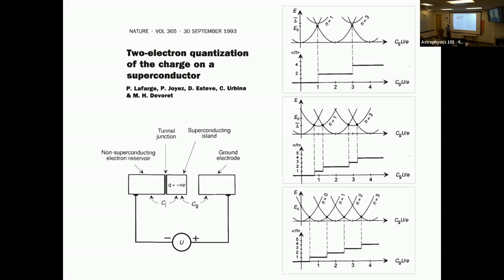But if the superconducting gap exceeds the charging energy, then that odd occupied state will be unavailable. And all that will happen is you'll go from 0 to 2 to 4 excess electrons. However, when that state is lowered in energy until it does cross, if by one mechanism or another I lower the superconducting gap, then I'll have a little region where the odd occupied state is available, and another little region where it's available, but mostly it's even, with a little step of odd occupied. And so finally, the system comes all the way down. The superconducting gap is gone. It can be a discrete or a continuous state, but there's no superconducting gap. And so finally, the odd occupied state is on equal footing with the even occupied state. And then finally, you recover 1E Coulomb blockade. So 2E, then even odd, then 1E as the gap descends below the charging energy.